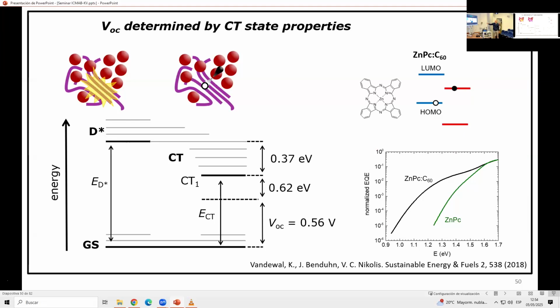Here is an example. It's not a good solar cell material, but it's a nice starting point. If you blend zinc PC and C60, energy levels are like this. The CT transition would be that one. You see this. This is neat zinc PC. Neat C60 is somewhere, not plotted. And this interfacial absorption, you see it's almost 0.2 eV away. Or no, here, 0.37 eV away from the gap.